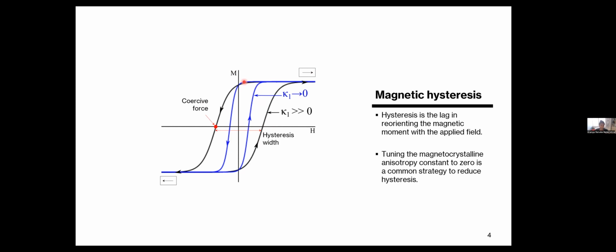So soft magnets are magnets that have very narrow hysteresis width. That is, you need a very minimum external field to switch the magnetization, and this is characterized by a very small hysteresis width. In the magnetic alloy development community, as well as the metallurgic community, one way in which you can develop soft magnets that have, for example, crystalline or long-range order, is to change the alloy composition so you can tune one material constant, called the anisotropy constant, close to 0. I'll talk more about this anisotropy constant later on in the slides, but essentially it's the penalty you pay when you try to rotate the magnetization away from the easy axis. So if you make the value of this constant close to 0, you should be able to switch the magnetization from one direction to the other with very minimum external field.